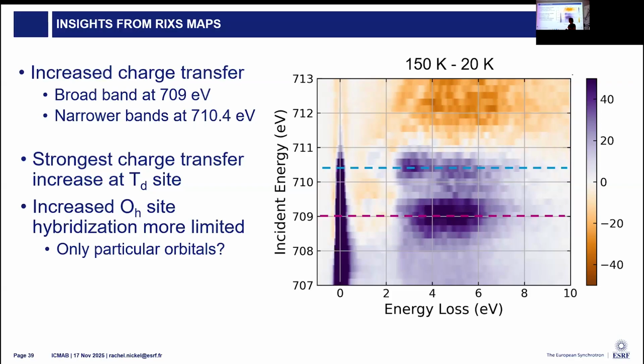With the films, we didn't have the sign of the characteristic low temperature transition, and so we didn't do the low temperature measurement. In general, the most information you can get from RIXS will come from a single crystal, where you can really map out properly both momentum and energy transfer. As you go to a thin film, where it becomes a two-dimensional structure, you have less access geometrically. And then with the powder, you have the complication of a powder average. So when it comes to simulation, you would have to basically simulate every possible point in momentum space, and then every possible intermediate and final state. And so that's one of the reasons why we don't have models right now for that.